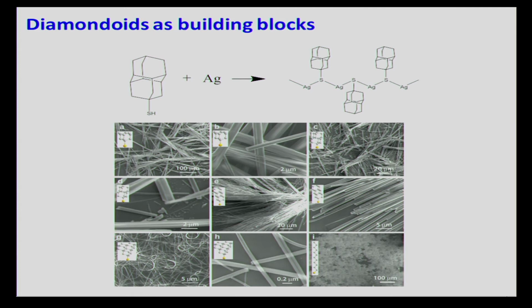What we see here is that as long as you use a diamondoid and mix that with a metal, you end up having these wire-shaped, highly crystalline materials. But when you use a normal hydrocarbon, that is one species with a long carbon chain, which does not have this cage-like rigid structure, what you end up having is this wax-like structure. It doesn't have a really crystalline appearance. So what this says is that the existence of the diamondoid and the interaction between the diamondoids really modifies the behavior of the crystal growth and really enables the growth of these highly crystalline materials.